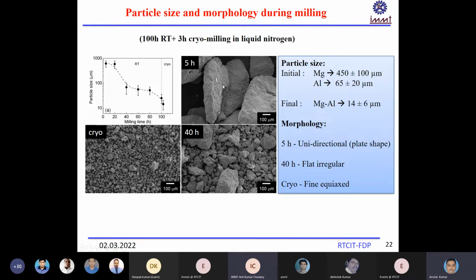I'm showing here how the particle size reduction takes place during the mechanical alloying. Initially, because it is a ductile material, the particle size increases, and further on, fracturing becomes dominant compared to cold welding. But even after 100 hours of milling, we could not get very fine particles. So that's why cryomilling: in cryomilling we reduced the temperature of the vial to around minus 40 degrees, and then it was again mechanically milled. So we get very fine particles.